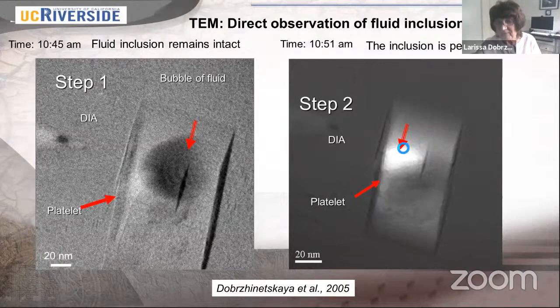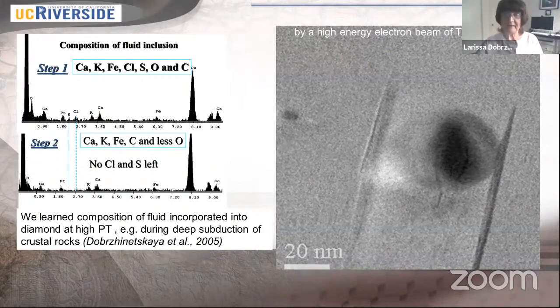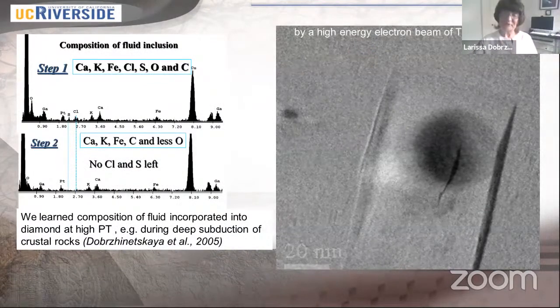And it happened. You see here, we have the hole. This is bright material, bright white material. It is a hole. The foil was perforated. We lost the fluid inclusion. However, if you look at how fast it happened, the beginning when we started to study was 10:45 a.m. and when the inclusion disappeared was 10:51. It took like 6 minutes to act because we had a very good guess that this is a fluid inclusion.